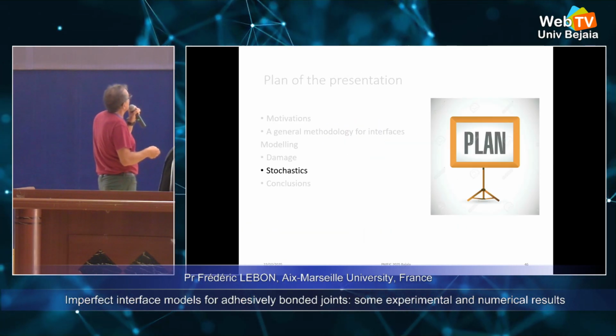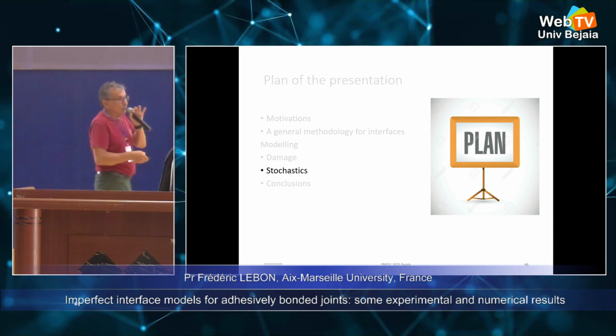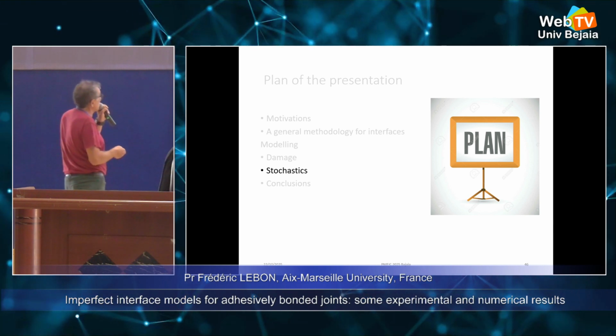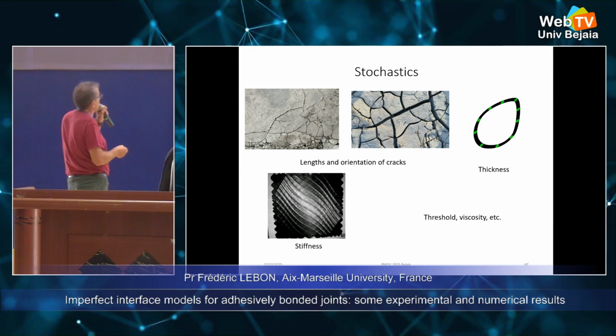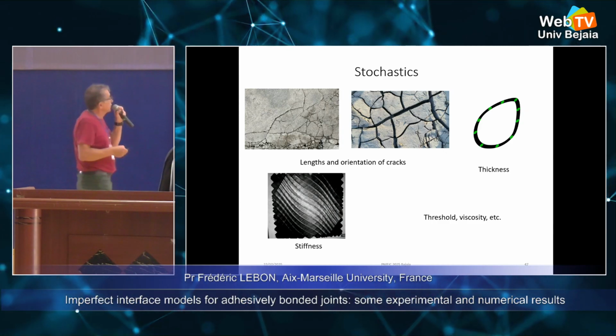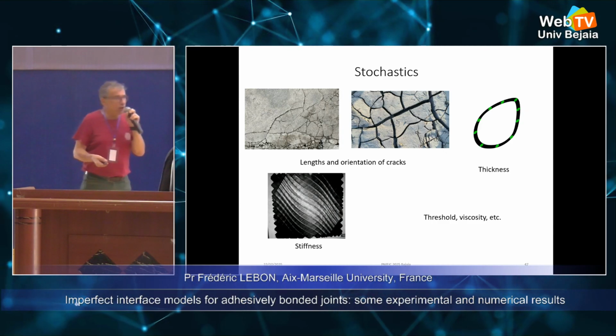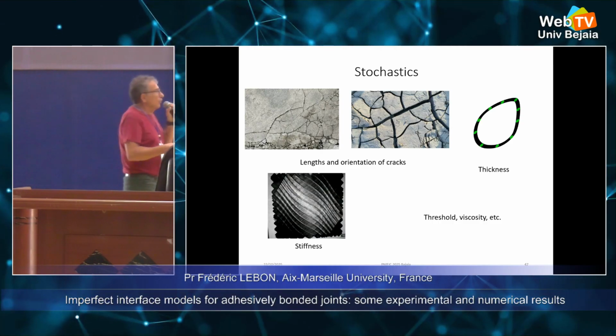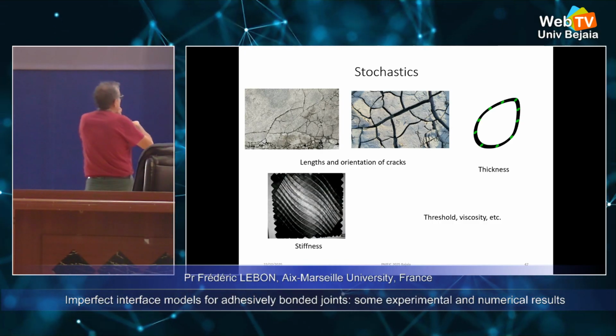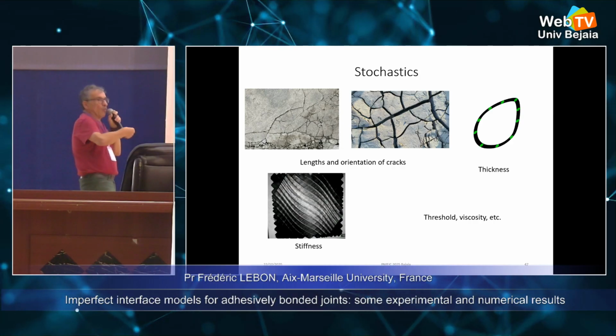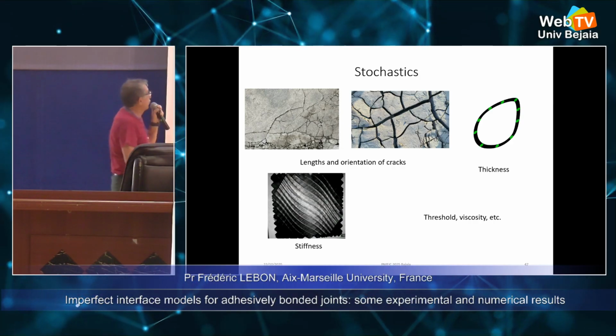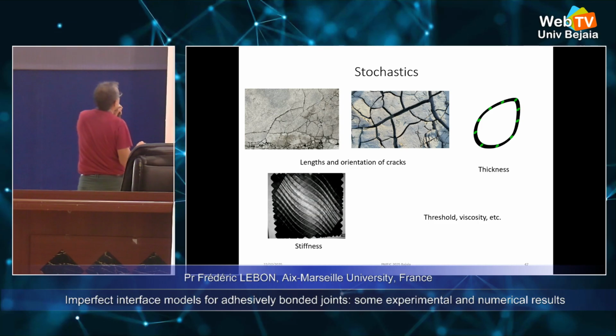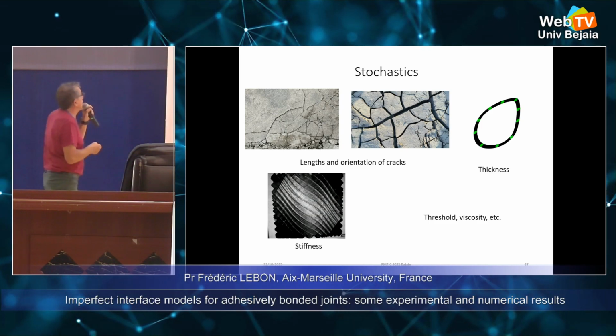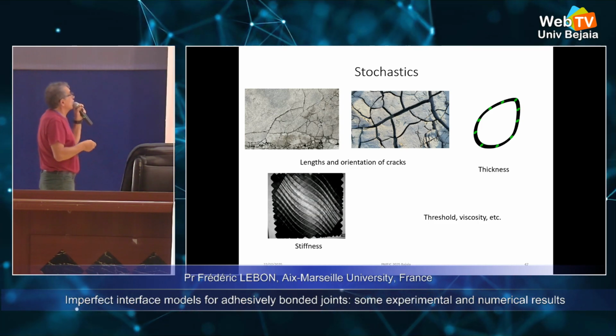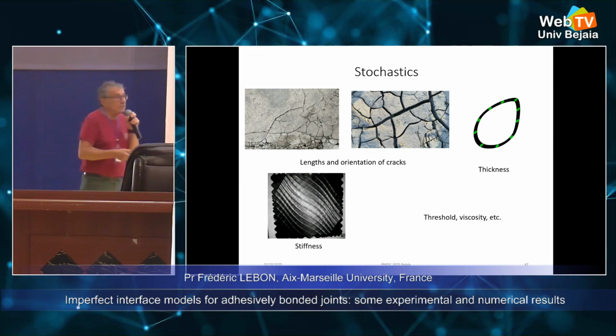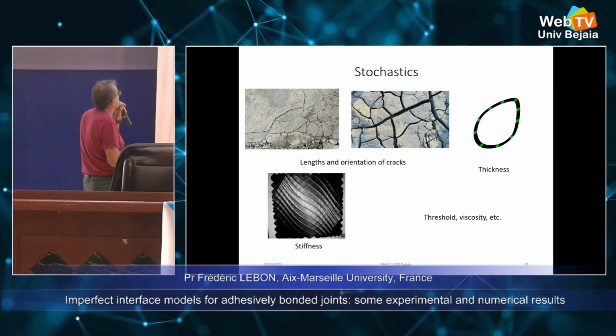Okay. I give a word on the stochastics. It is possible to introduce two stochastics because, in fact, the idea of the introduction of micro cracks is very simple. It's a line in one direction. But if we look at the local level, we can see that, in fact, the length and the orientation of the crack is quasi stochastic.